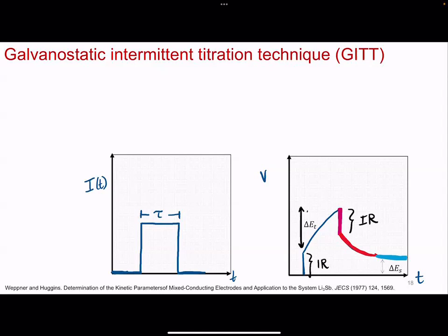And that's really difficult. For certain materials, that's just intrinsically difficult, because lithiation of heterosite FePO4 into orthorhombic LiFePO4, the olivine structure, is almost immediate.